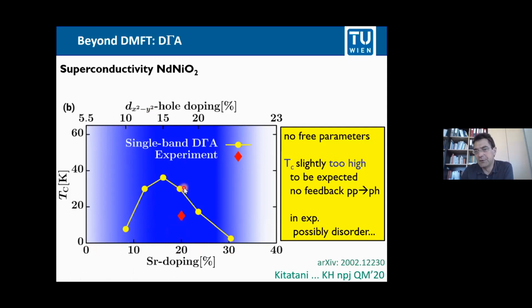The TC is a little bit too high. It would have been very simple for us to increase the U. Then TC would go down and we would be on top of the point here. But we think that the way we did it without adjusting parameters, you might argue about this ad hoc enhancement of the U, but that's from experience. We prefer to have it here, and we think there are good physical reasons why it should be a little bit too high. I mean, we are talking here about 15 Kelvin. That's tremendously good for so difficult to calculate a quantity as TC without adjusting any parameters.